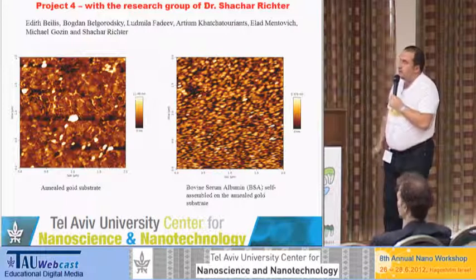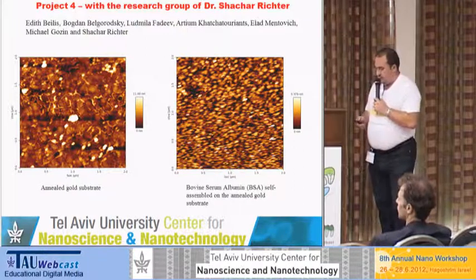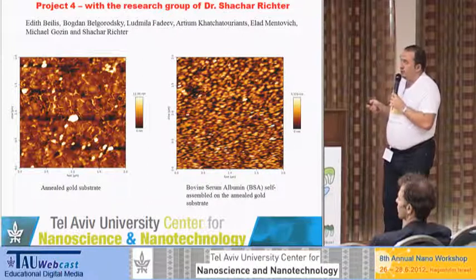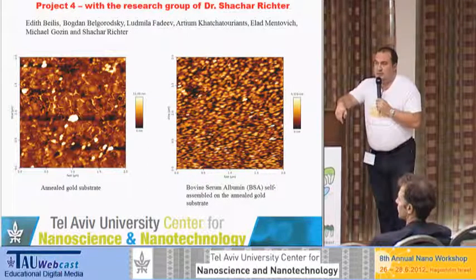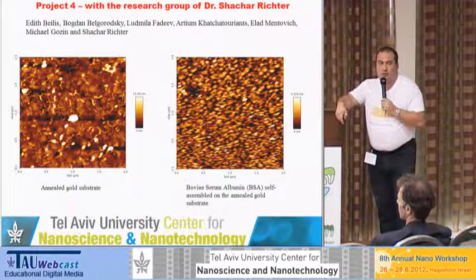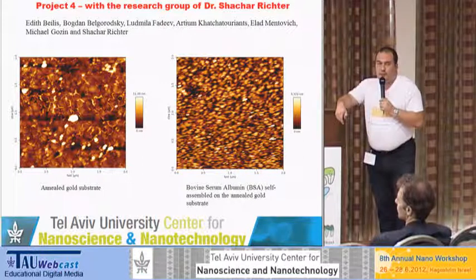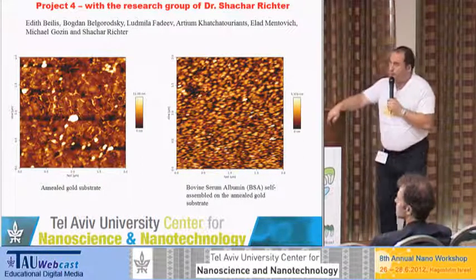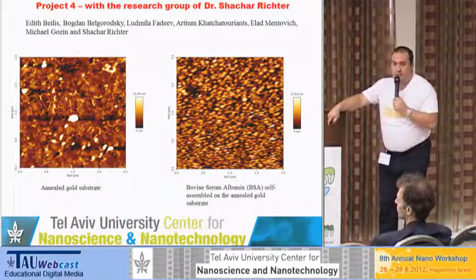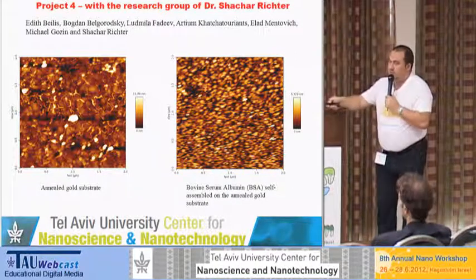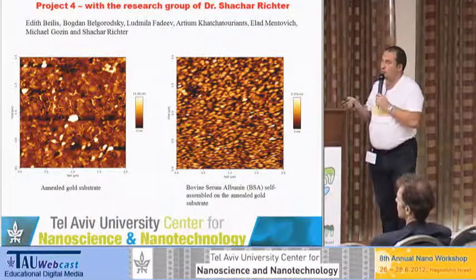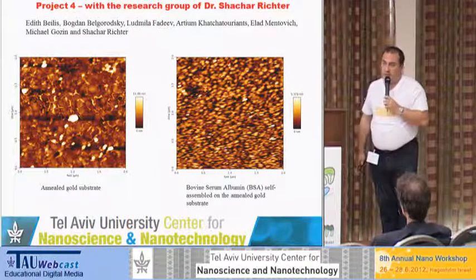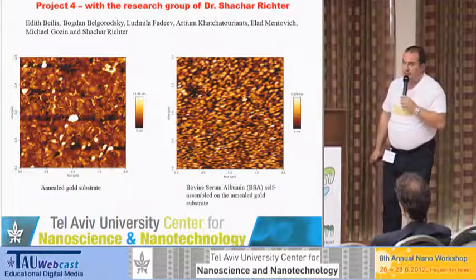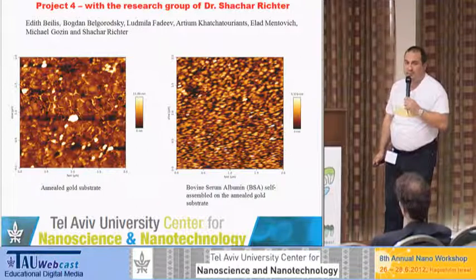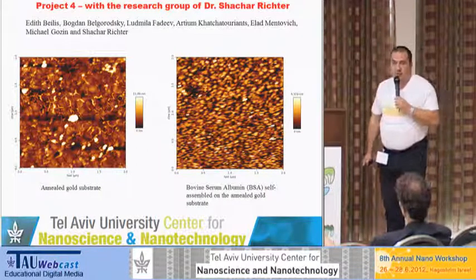The next project I would like to present is with the research group of Dr. Shachar Richter, and they investigate adsorption of BSA, bovine serum albumin, doped with also other additions, other proteins, on gold-coated surfaces. So they take a chip of silicon, coat it with gold, then they anneal it in order to flatten it, and then they adsorb bovine serum albumin on this surface. Bovine serum albumin is a very famous protein. It is abundant in the blood, has also remarkable properties.